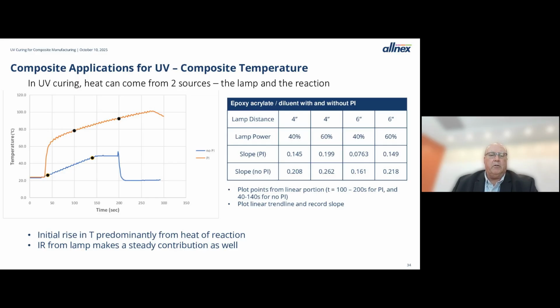So just to show you in this diagram here on the left, the blue line is a formulation where I've left out the photoinitiator. And when we turn the lamp on, about 35, 40 seconds into the run, you see a temperature rise, and that is solely from the heat from the lamp. So over the course of 2 or so minutes, we're doing a 20 degree jump in temperature. The orange line represents a fully formulated material with photoinitiator. When you turn the lamp on, you get a very, very steep rise in temperature, and that's due to the heat from the reaction. And then you go back to a slow, steady rise that's predominantly heat from the lamp. So the heat of reaction does generate a big temperature rise in your composite material.